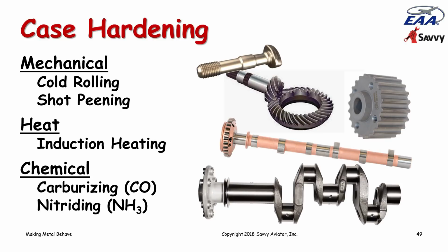Most crankshafts are case hardened using another process called nitriding, which is very similar to carburizing, except that the part, instead of being baked in a carbon monoxide atmosphere, is baked in an ammonia gas atmosphere. And during that baking process, the nitrogen winds up diffusing into the outer surface and creating a very hard outer surface that's 10 or 20 thousandths of an inch thick. So these are all ways of case hardening material.